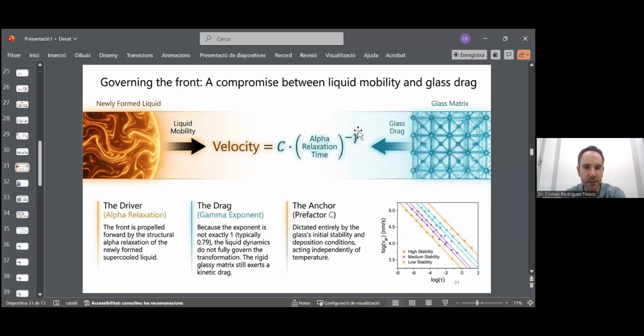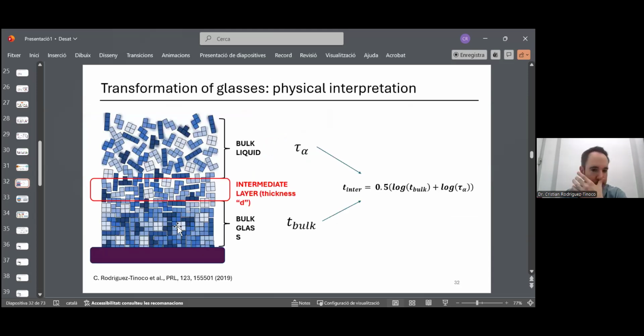Okay, so what does it mean? This is the expression we saw before: alpha relaxation time to a power of around 0.8. But we also have this prefactor, this C, which depends on the stability of the glass. So it is not only the liquid which is governing the transformation, but we also have some influence of the glass matrix. And it can be understood in this way.